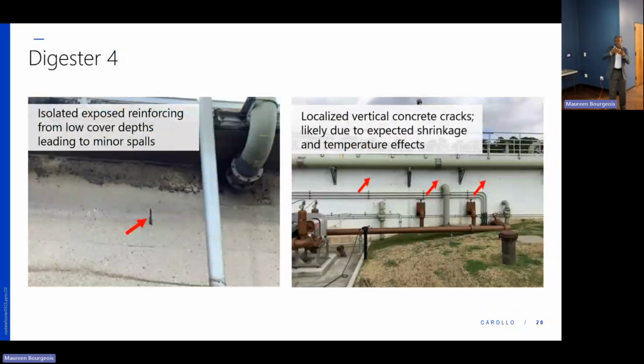The reinforcing is too close to the edge, so you don't have that 2 inch cover, but that's an isolated incident. So we captured that also occurring there. And then as we walked around the structure, we see local vertical cracks, and that's typical, very fine hairline cracks. That's typical because usually with concrete, you have cycles of temperature, cold, hot, all that going on, and that allows the concrete to expand and contract. And so you have these temperature or shrinkage cracks. None of these that we saw were leaking as far as we saw.